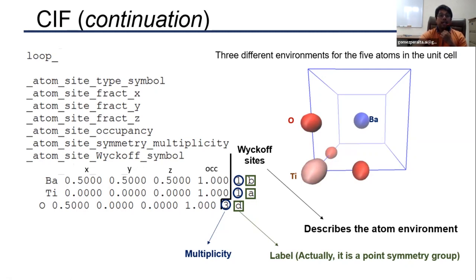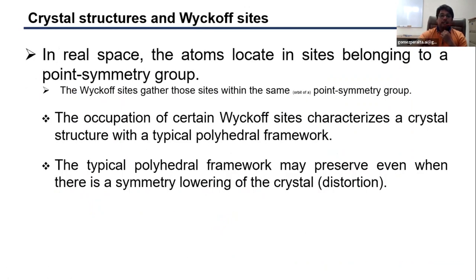And in crystallography, those atoms having the same chemical neighborhood share the same point symmetry group. There is another way to say this, and this point symmetry group corresponds to Wyckoff sites. Wyckoff sites gather positions in real space with the same point symmetry group. And instead of describing the 3 oxygen atoms, you only need to describe one of them, since the other 2 atoms basically see the same neighborhood. In real space, for atoms located in sites belonging to a point symmetry group, the Wyckoff sites gather those sites within the same orbit, to be more specific, the same orbit of a point symmetry group.